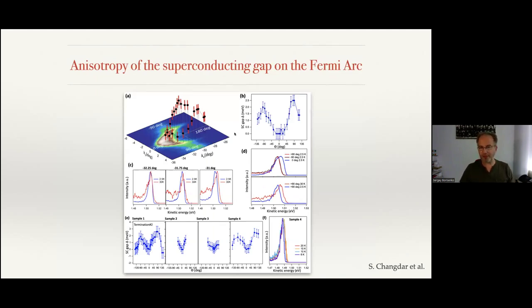So, having this precision, of course, one asks the question, how about the superconducting gap as a function of momentum? And it turned out that the dependence is very interesting. And as we saw this, we immediately went to our theory colleagues, but the magic word node, somehow we didn't realize that. Then we heard from a theorist that indeed, we have the superconducting gap, which is finite at the wings of the arc, and which is 0 in this direction. It means that now we have the superconductivity, and this data just support this.